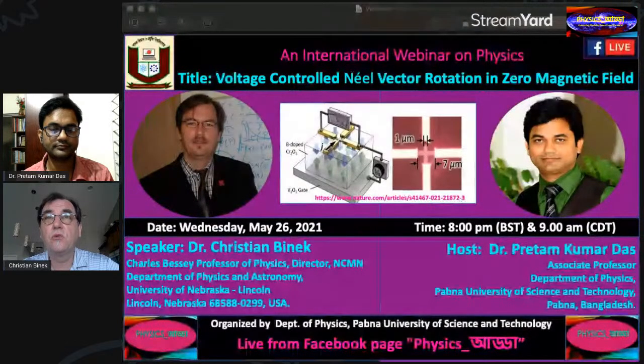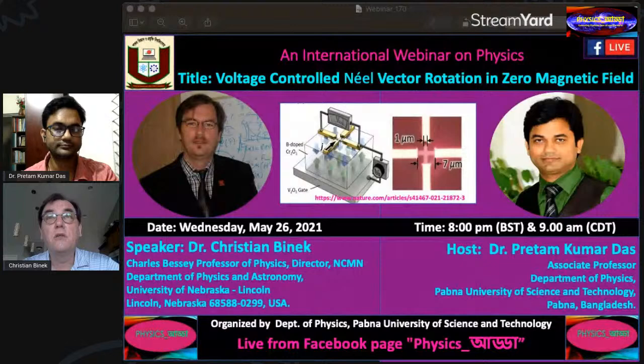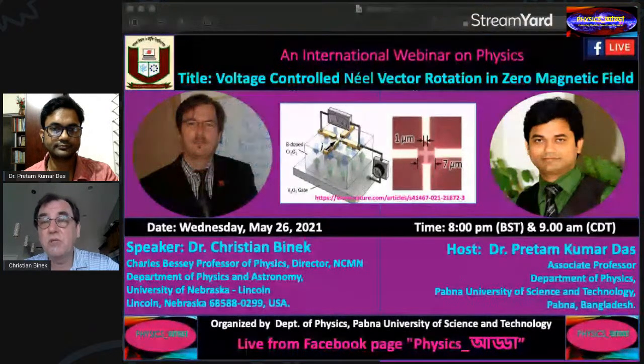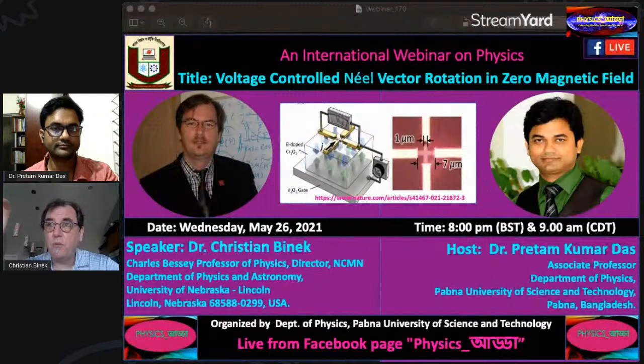That gives rise to a dipole, and that is, by the way, the reason why if you apply an electric field to pure water, you would have a strong dielectric material, because all these dipoles, which at first are randomly oriented, would align in the presence of an electric field. We call that dipole orientation, and that gives rise to a very pronounced polarization. And in our chromia, something very similar happens. You have locally these molecules, if you like, this big, that have a dipole moment, and in the presence of an electric field, all these dipole moments align in the same direction and create macroscopic polarization.